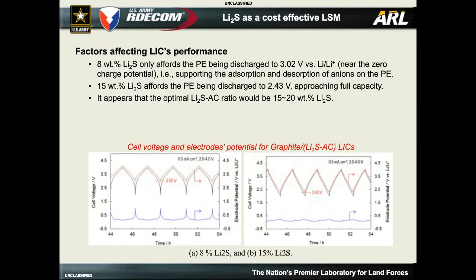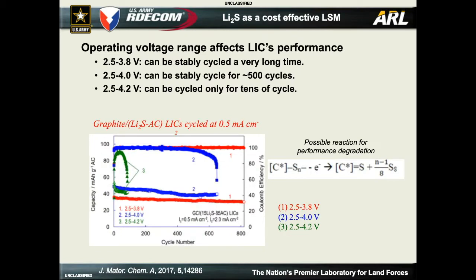This just shows that at 15 weight % lithium sulfide, if you can read this chart here, you can see on the right, you've lithiated your graphite electrode, and you're able to cycle the full cell pretty well. So this approach, again, allows you to do the pre-lithiation, and it would be a lower cost approach to forming an LIC. And this just shows cycling here.